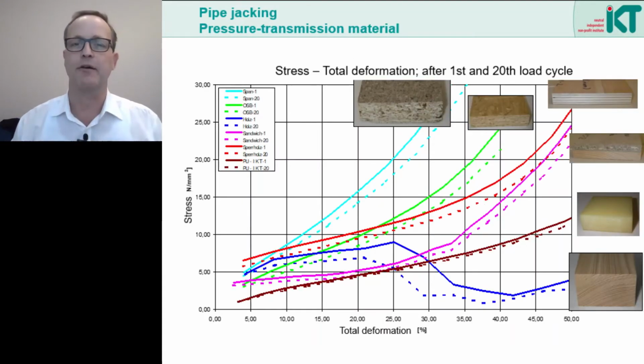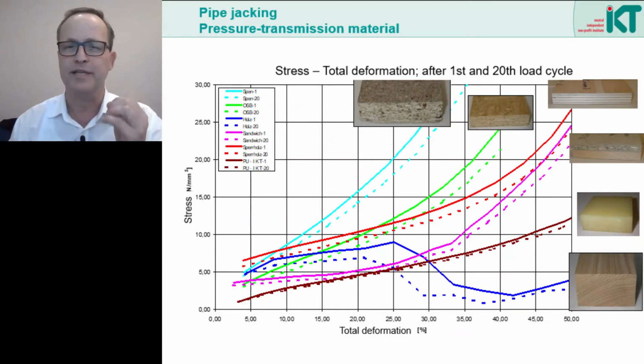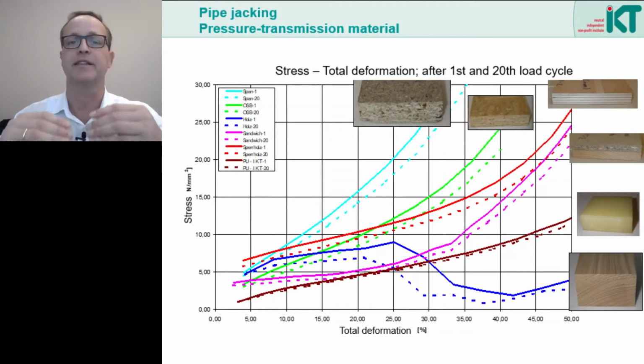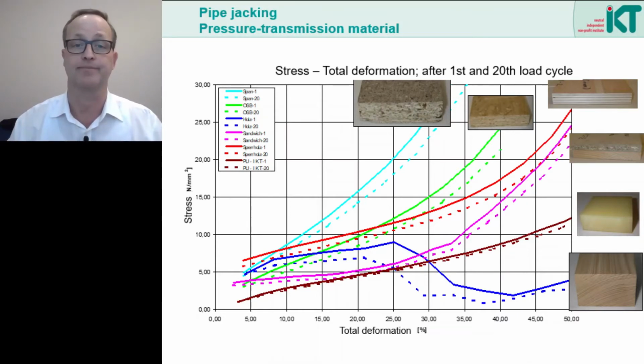Against this background, it is important to have a precise knowledge of the material behavior of the pressure transmission means. And there are big differences. Here we see the stress-strain curve for 6 different materials. There are 2 curves for each material. The solid line represents the deformation at the initial load cycle. The dashed curve represents the deformation that occurs after 20 load cycles.